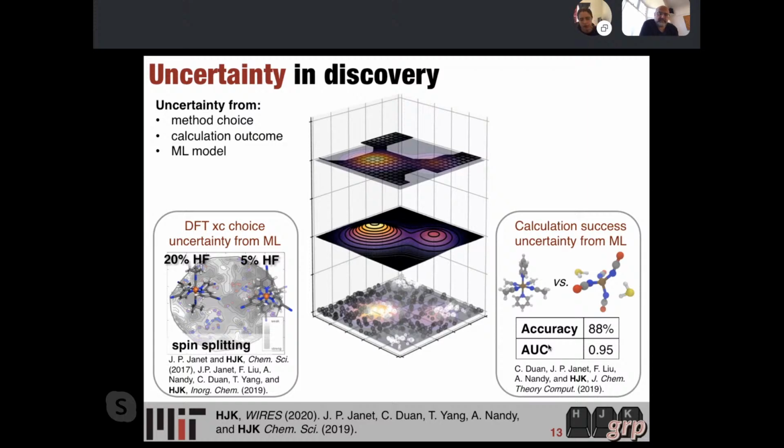So the first question. In the very first work, we looked at a wide range, all the way from lasso and random forest to neural networks. In practice, I'd say our typical workflow now is we use random forest to rank our feature selection, so to assess feature importance, but the prediction models we use are typically a kernel ridge regression model and a neural network model. And our rationale is that for our data set sizes and feature sets, if we can't get the KRR models predictive, that's a sign that the feature set is either incomplete or that the data is dirty. So we use that as a quick assessment of how well we're doing.